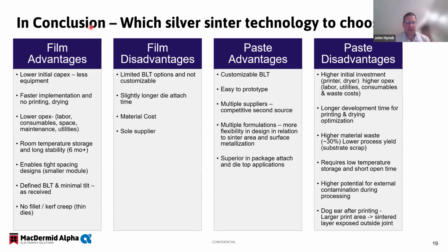The advantages to paste: it's familiar, bond lines are customizable, it's super flexible, like I had said, and it's very, very familiar as far as the processing equipment goes. But the disadvantages are the initial investments are higher, the processing time can be a lot longer, especially with the drying process involved. It's susceptible to high material waste. I mentioned earlier, we've seen up to 30% loss, or it's just only 70% yield, because so much of the paste can get lost during a print process, for example. They can require low temperature storage and a short use time. And then there's high potential for external contamination.